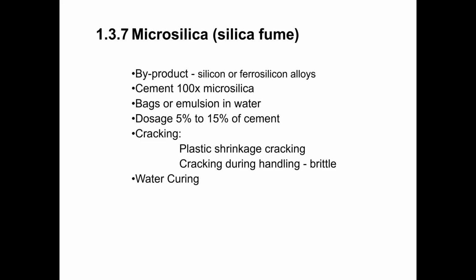Also, there's an increase in potential for cracking the concrete during handling. Silica fume concrete, while it's very strong, while it's very dense, it does tend to be a little bit more brittle than regular concrete. So if you have a sharp edge, a sharp corner, then that corner may be more susceptible to spalling than it would if it was just a regular concrete mix design. So because of the potential for the concrete to dry out quickly and lead to plastic shrinkage cracking, water curing may need to be explored when using microsilica.